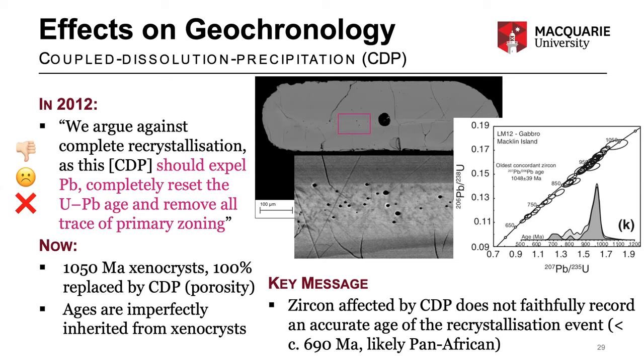So today, I would interpret that most grains are xenocrysts in the Charnockite. These have been variably affected by coupled dissolution precipitation. In the backscatter electron image, which was collected just in the last few months, we found evidence for microporosity in the zircons. The key message here is that zircon, which has been affected by coupled dissolution precipitation, doesn't necessarily faithfully record an accurate age of the recrystallization event. In the case of the Mawson Charnockite, I now say it's probably a Pan-African aged intrusion.